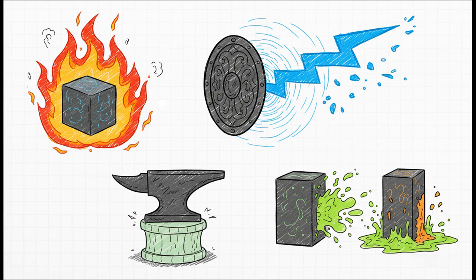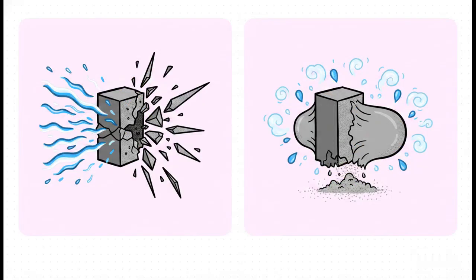But its true superpower? Its basic chemical nature makes it highly resistant to aggressive calcium-rich molten slags. Acidic silicates would dissolve other ceramics like alumina on contact, but MgO, it just brushes them off. But of course, every superhero has its kryptonite. First up, thermal shock vulnerability. Magnesia has a relatively high thermal expansion coefficient for ceramic. If you cool it too quickly, those massive thermal stresses cause it to crack and shatter. Second is hydration risk, and the irony here is actually staggering.